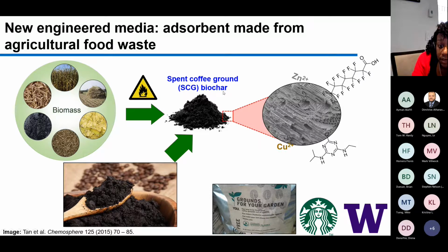And if you zoom in and take an image of this biochar, this is an image that my PhD student captured, you can see that depending on the feedstock, you can have large networks of pores present in the biochar, and contaminants like heavy metals and organic compounds can diffuse into the pores to be effectively removed.